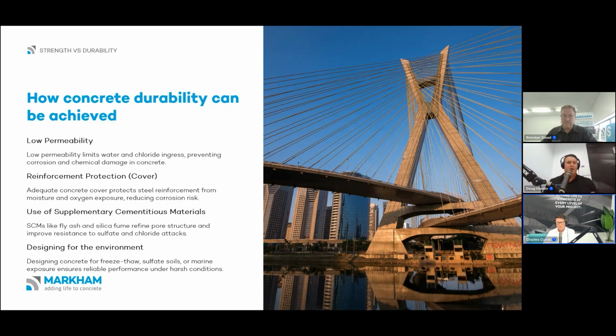It's not going to let the water come through like a river. What you are forgetting there is that it is still getting through to the reinforcing steel over time. So it might be holding that water in that tank, but it's not stopping the moisture getting through the concrete and taking contaminants through to that reinforcing steel. So yeah, that's just something I wanted to highlight there. Not to mention too, the higher the MPa, the more chance of cracking, and then it using those cracks to progress as well.